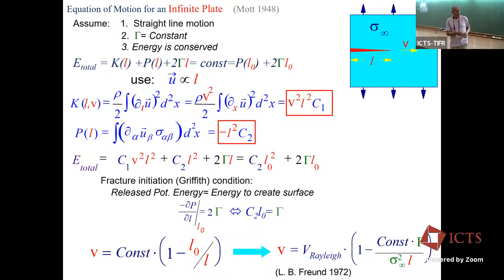This is also telling us that no matter how long, this can become infinite, we have an asymptotic velocity here. Cracks can't go any faster than this constant. Now, when you solve the problem correctly, you find that this constant is something called the Rayleigh wave speed. Does anyone know what the Rayleigh wave speed is? I'll show you. The speed at which a disturbance moves along a free surface.